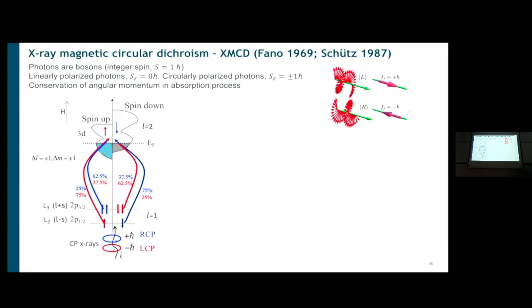Circularly polarized photons have a spin of plus or minus 1. It's helicity. So when you come in with a circularly polarized photon and you excite a photoelectron, the spin of the photon has to be conserved. So you transfer that angular momentum to the angular momentum of the excited photoelectron. So the colors here are showing that if you come in with right circularly polarized X-rays, you see 75% spin down and 25% spin up. So you excite mostly one color of spin. And if you reverse the helicity, the red, you see 75% here, you excite the other color of spin.